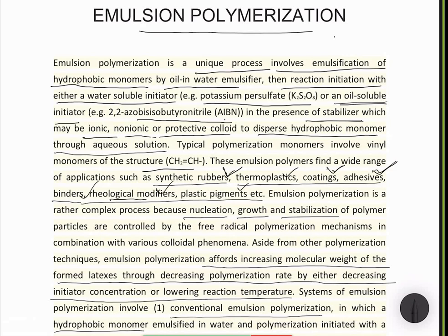Suspension is also a heterogeneous technique, but this emulsion is widely different from all these three previous techniques, because this polymerization is rather a complex process, and it constitutes particle nucleation, their growth, stabilization, and finally dissipation of the reaction to form finally these polymer latex particles. And this entire process is associated with several colloidal phenomena.